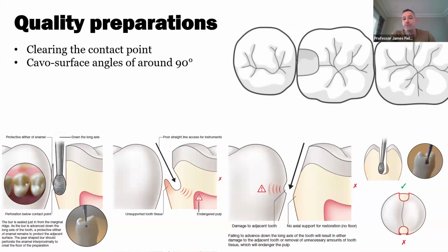Good idea, as you can see in the diagram at the top, to have cavo surface angles of around 90 degrees. And that means that we've got a degree of robustness both to the tooth structure that's left, but also the restoration that we're placing. If we allow those cavo surface angles to become acute, then we find that we either get degradation of the margin because we get slight microfractures or larger fractures of tooth structure or of the restorative material. And actually, bonding things in place isn't really just enough to stop that from happening. And even if the pieces did stay in place, you still have fundamental cohesive failures in your restoration or at the tooth interface, which will cause micro leakage.